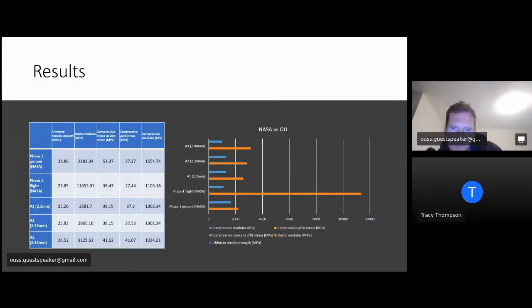So here's my results. I think you can ignore that chart on the right because it's completely out of range. So just look at the table here. So NASA, the first two rows there, those are the NASA samples that were printed. And then the last three samples, sample A1, A2, and A3, they're my samples. And as you can see, they're not too far away from the phase 1 ground samples that NASA made. There is a bit of an anomaly there with the phase 1 samples from NASA, and I think that's just a test setup issue, which is represented by the massively out of range phase 1 bar there. So yeah, I had a good baseline measurement, and it confirmed actually that my tests were good, and I was very pleased with that.